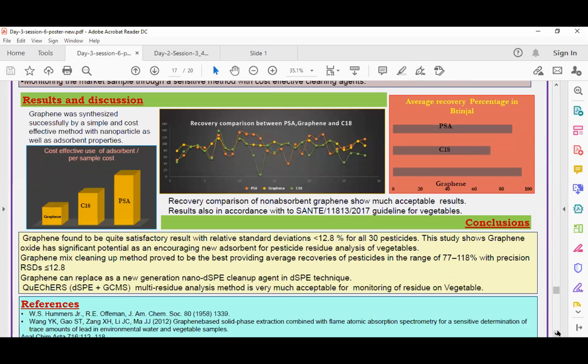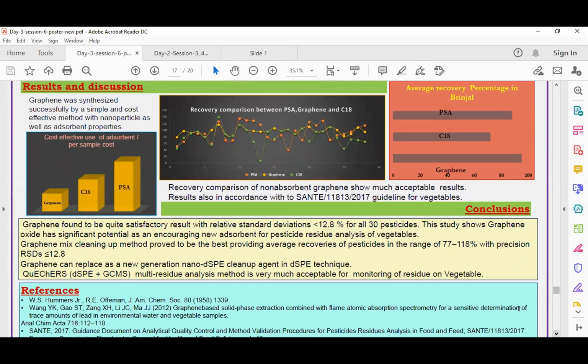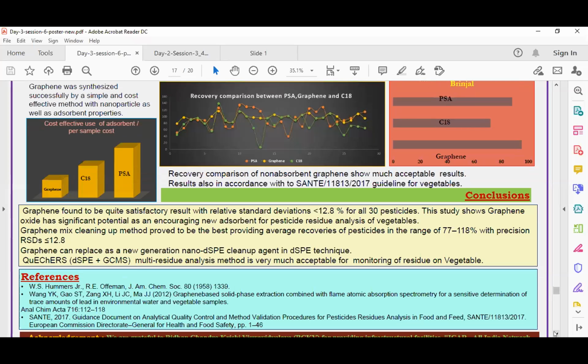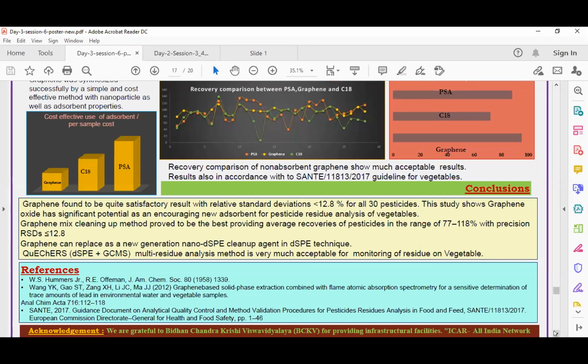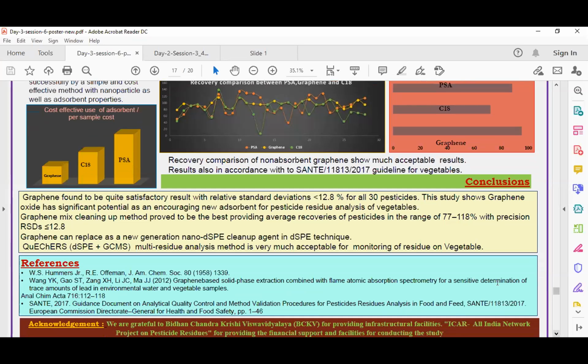We have also studied different matrices like cabbage, chili, and so on, with different content of pigment also. And graphene oxide shows good results among those substrates. The conclusion is that the graphene was found to give quite satisfactory results, with a relative standard deviation of less than 12.8% for all 30 pesticides. We selected 30 pesticides, and the study shows graphene oxide has significant potential as an encouraging new absorbent for pesticide residue analysis of vegetable.